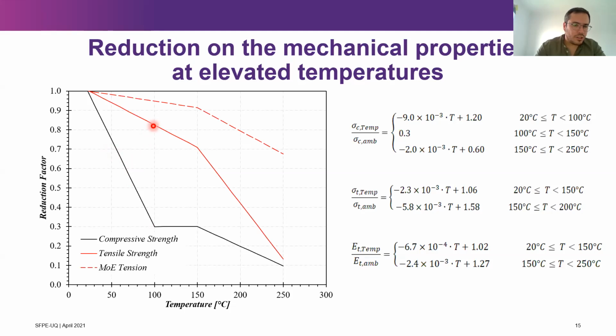So the reduction in tension is not that critical. And obviously a reduction in the modulus of elasticity again is not that critical. But after 150 degrees, where we observe the onset of pyrolysis, the reduction is way more considerable. And then after 250, the material is completely charred, and the strength and stiffness of bamboo can be neglected.